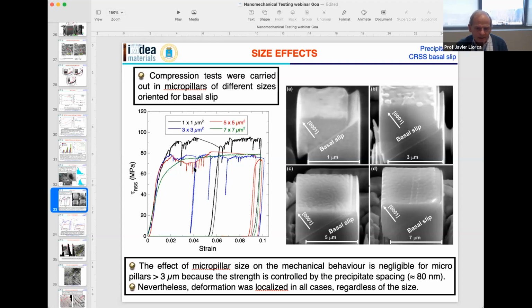What you can see here immediately is that, even though we have localization of the deformation in all cases, the size effect when you have precipitates is much smaller. Actually, between 3, 5, and 7 micrometers, the curves are almost superposed. So the presence of the precipitates significantly reduces the size effects. That's good news for micromechanical testing.